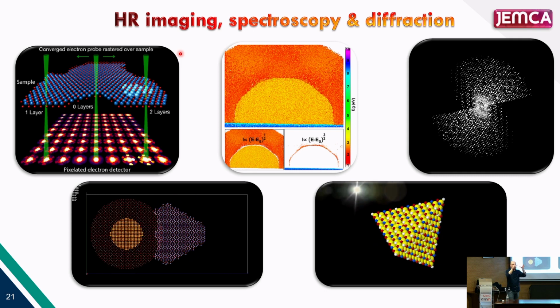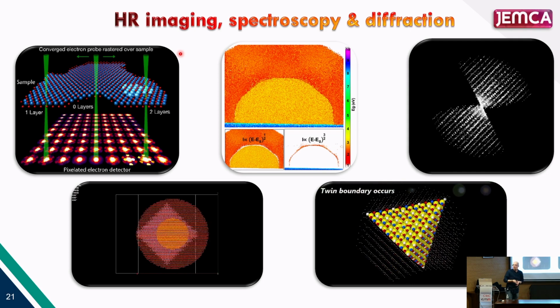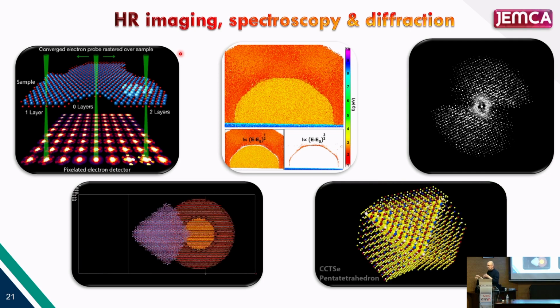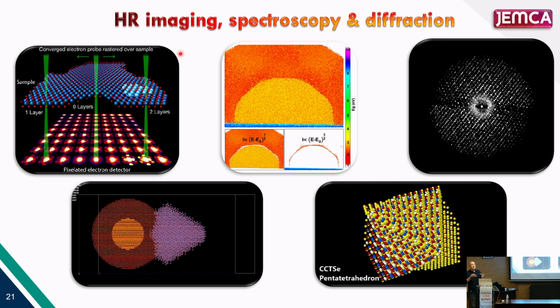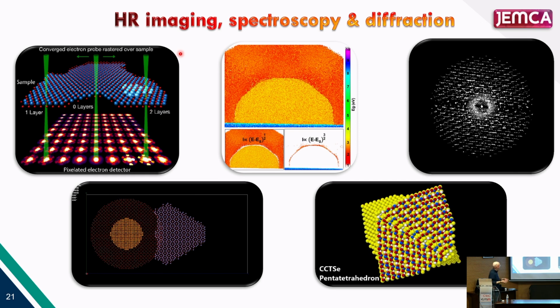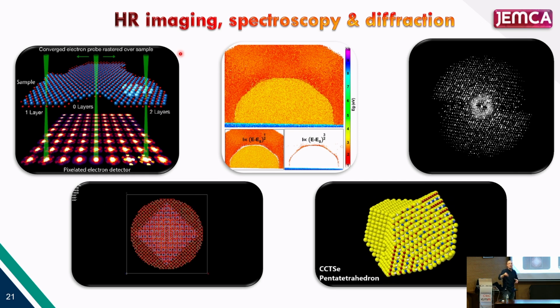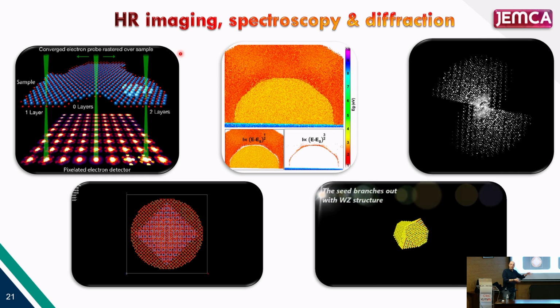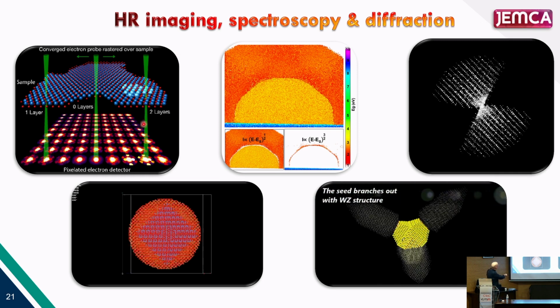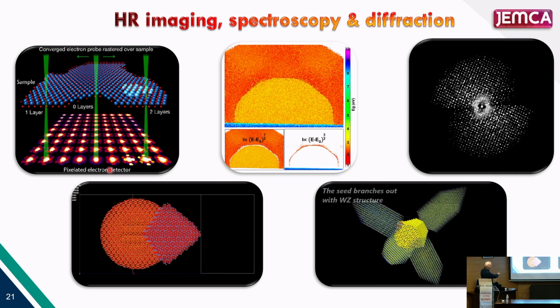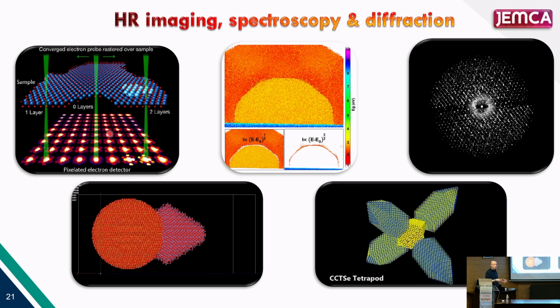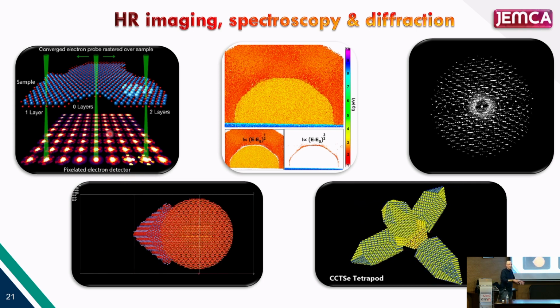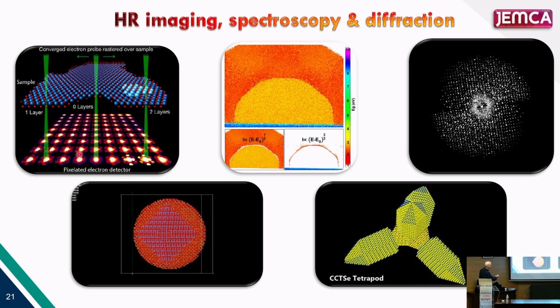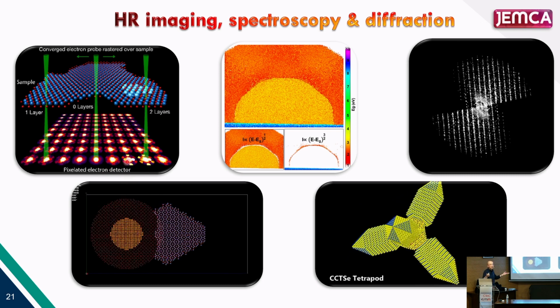So when your electron is crossing an atomic column, it's behaving depending on the electric field that it found. Depending on the interaction of this electron with your material, it will be deflected or not. This is what you can measure with this kind of technique called 4D STEM. So you are measuring the deflection of your electrons when crossing the sample, and with this, you can do ptychography, for example.